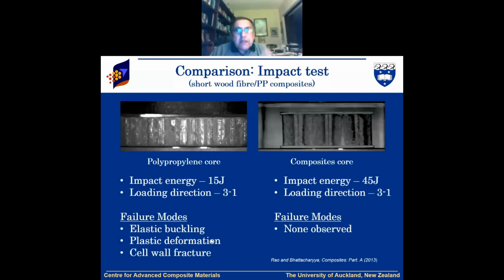Now, this kind of material, when you have got fibers introduced, normally in a sandwich panel, in a core material, the core does not have any reinforcement. So we thought that if we could reinforce them, if we could manufacture the core with some short fibers reinforcement, even with polymeric materials, we could get much higher impact energy, and it was a very attractive part. However, we did study the buckling, failure modes, everything, and then we published a paper also in Composites Part A. So this kind of product can take quite a bit of impact property. I'll come to that, why we were interested in that.